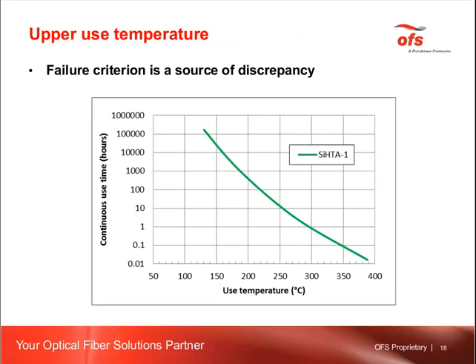One of the examples of the correlation obtained from the TGA data is shown here. So that is the curve for one of the coatings, with the x-axis equal to use temperature, and the y-axis the continuous use time. For this coating, the 20-year lifetime, according to our TGA criterion, corresponds to 130 degrees C. Now, can this fiber be used at higher temperatures than 130? Yes, it can be used, for instance, at 300 degrees C, but for a shorter time, about 1 hour.